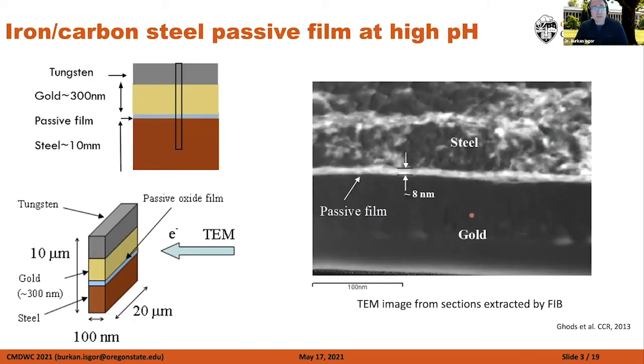Now, this is what we started 15 years ago to look at. The first thing we wanted to do is look at the passive film. So we used TEM to do that. You can take an iron or carbon steel, create a pristine surface, put it in a simulated concrete pore solution, a high pH environment, and develop a passive film over time.